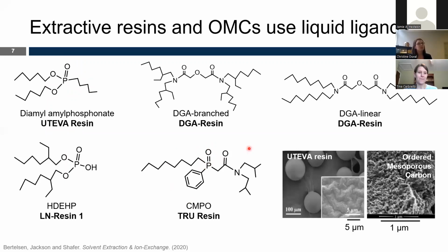Some of the more emerging ones, I would say, that are gaining a lot of popularity these days as we're looking at separating trivalent lanthanides, which are also rare earths, are some of these DGA, diglycolamide functionalities. You'll see here we have these 3 oxygens. They tend to form a more rigid structure. Usually you get a 2-to-1 binding motif between your ligand and your ion. And so these were all, in that same way, incorporated in a physisorbed way into those resins.